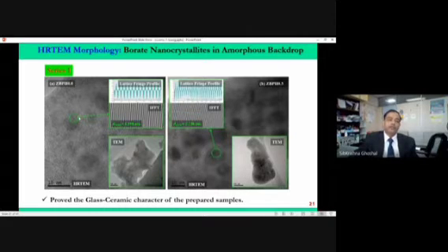We look at some chunk in the material through the HRTEM study. Then we look at their crystallinity. This is called the lattice fringe profile, through the SAED or FFT, the inverse Fourier or fast Fourier transform, or you can do SAED, selected area electron diffraction. From there you can find the lattice parameter. And these lattice parameters, when you check with the JCPDS card number, you see this corresponds to the borate crystals, and that clearly indicates that we really formed it. So this is the proof that we are working on glass ceramic, not just glass.